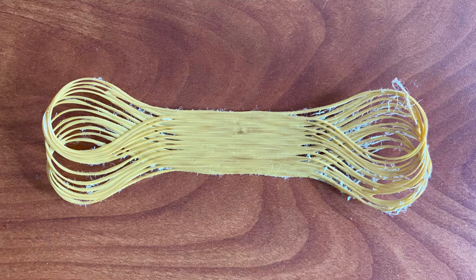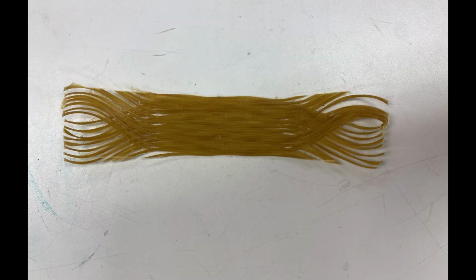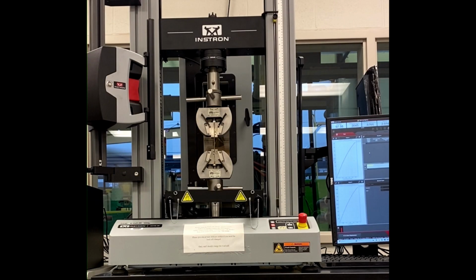With this, we were able to do even further testing. We wanted to determine the strength of this 3D printed part compared to that of other resin composite fiber created through previous means. To do so, we cut our print sample into a standardized sizing and had it undergo a tensile test in order to determine how much force it took to fracture it.